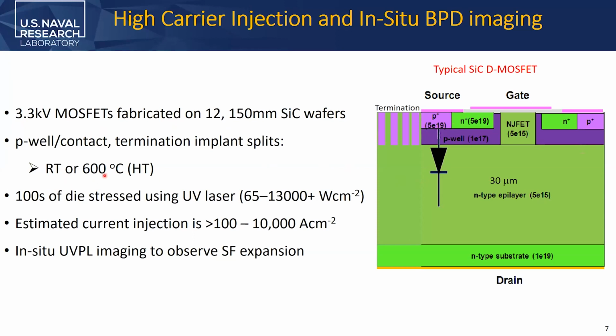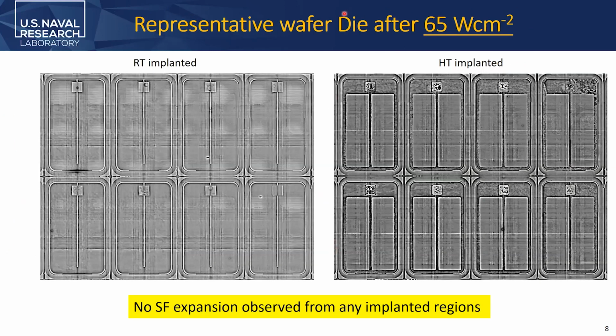We had room temperature versus high temperature implantation, and then we stressed hundreds of die using different power levels, and we inject the carriers using UV illumination. And this is a simulation of a high injection current, like a pulse. So it's similar to a lightning strike, 10,000 amps per centimeter square, for example. And then we observe. So when we do it at low current densities or low carrier densities, both the room temperature as well as the high temperature, we do not see any defects when we image them.